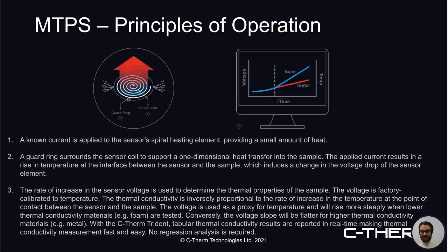Now, in this heightened example here with two very different materials, a foam, something very low in effusivity and low in conductivity, will result in a much steeper rise in temperature if you were to dive into the raw data. Whereas a metal, something higher in performance, would be much flatter as it's much better at dissipating that generated heat. So this is the core idea behind the measurement. You're monitoring that change in temperature that occurs over time.